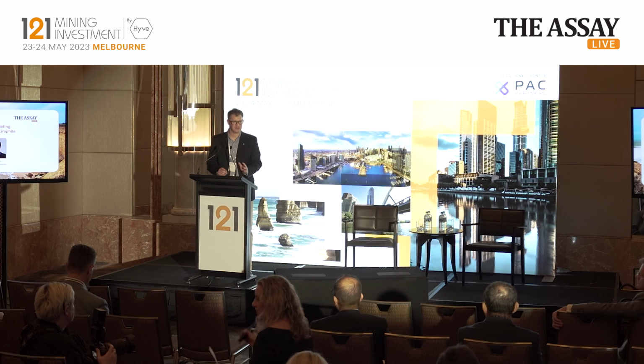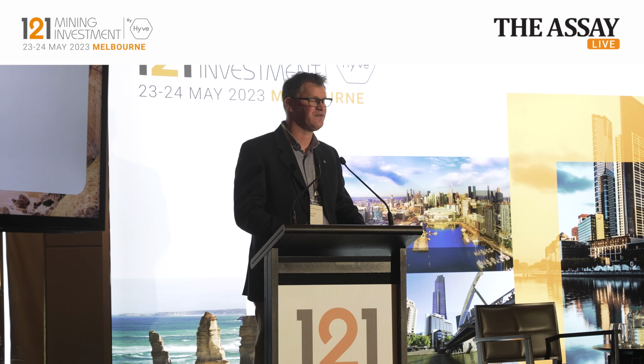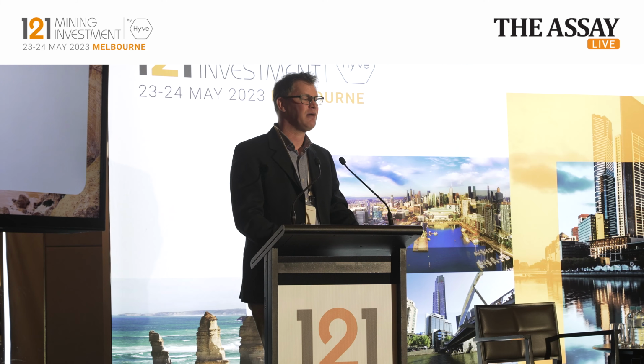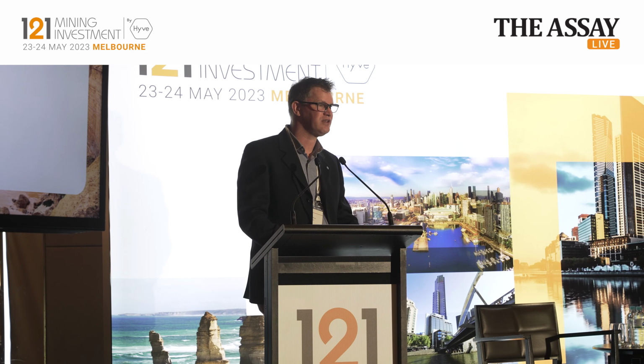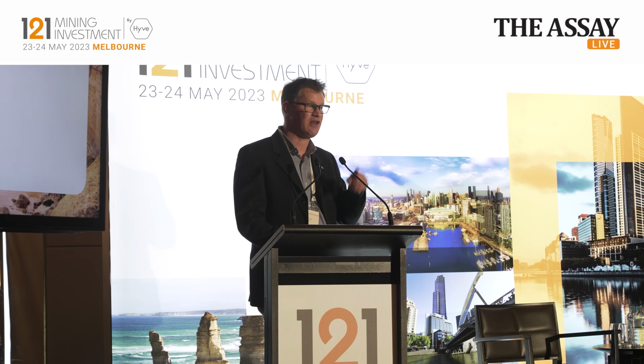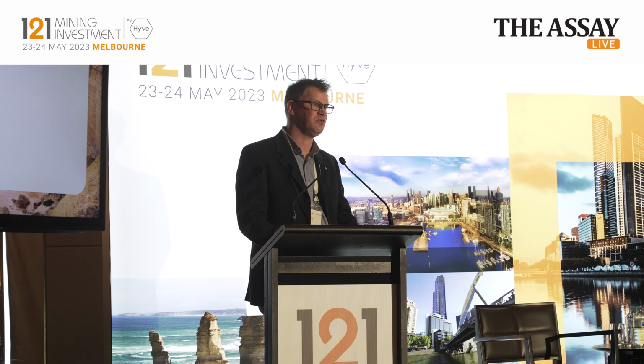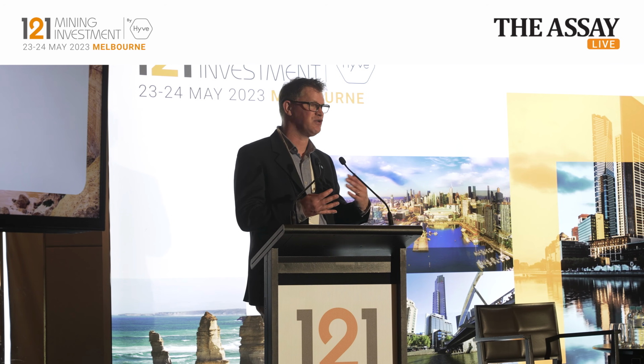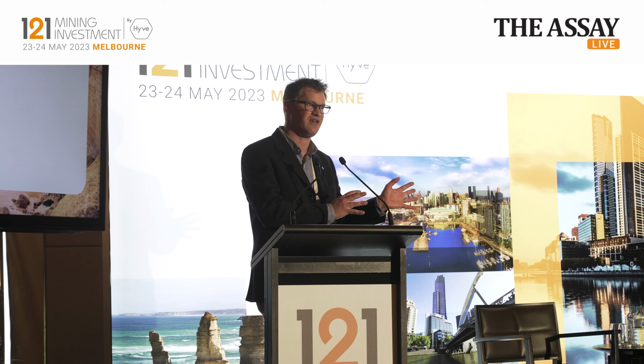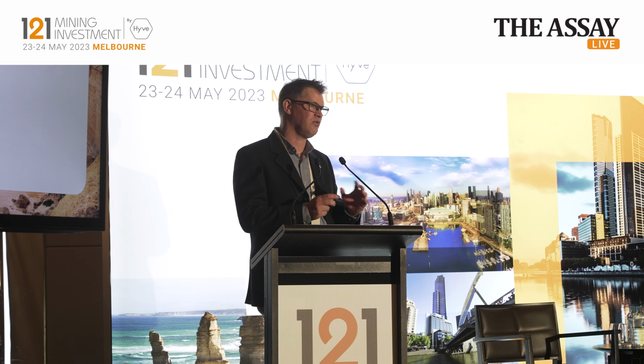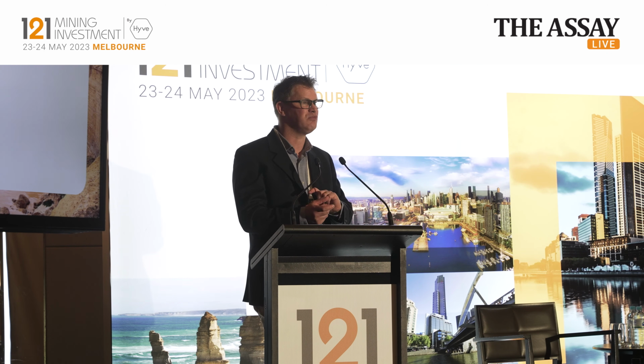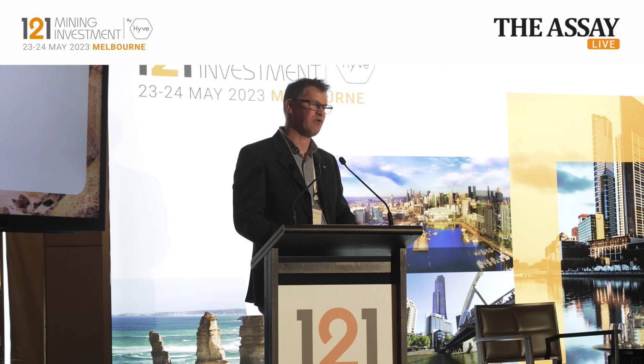I do understand that Westwater Resources is also using an HF-based final step purification at their Kellyton plant in Alabama. But we at CSIRO have actually developed a caustic processing method, which is able to regenerate that final step purification solution. So we can take out the impurities from that solution and reuse it again. It makes it far more sustainable, and we can tune that to the impurity matrix. If we do good characterization at the initial step of the graphite process, we can work out how we tune that caustic to remove that impurity matrix quite easily. And we've done that for 4 miners now here in Australia.